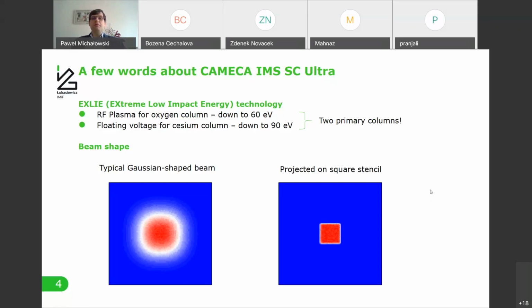However, the problem with it is that usually when you apply so many changes, like very low impact energy, you cut just a little bit of the beam, and then also you change the incident angle, as I mentioned, you lose a lot of the signal intensity. So for this, I made something that I call the dedicated SIMS procedures.